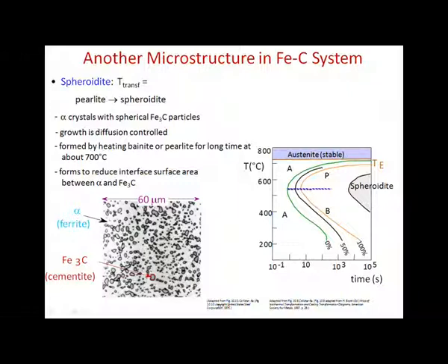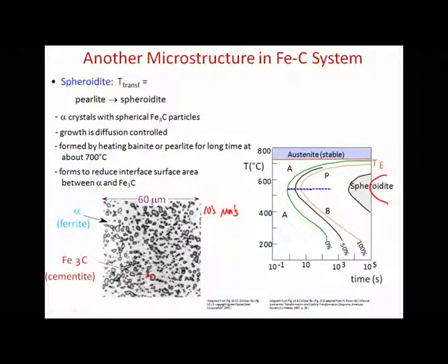Okay, and you can see here, it's the second nose. What is this C shape, or the nose shape? What does that mean? There are 2 processes at play, 2 competing mechanisms. It's still nucleation and growth of these things. We've got the nuclei there, and then growing, starting to form this shape, separating a lath from there. But now they're on the order of tens of microns. That's 3 orders of magnitude change in the size of the particles. Good or bad? Bad.